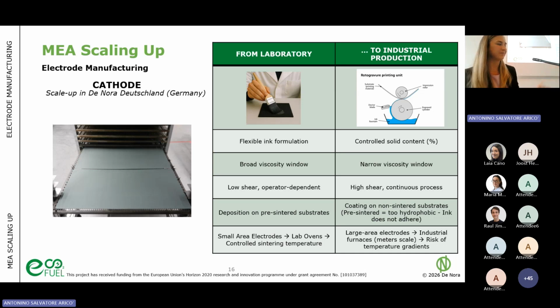Something is okay. And also in this case, what we need to consider, starting from the lab to the industrial scale. In the case of the lab, what we normally do is using a brush. So that's what we do in the lab. And in this case, we can work on flexible ink formulation, because it's operator dependent, the way we do the GDE. It's a low shear instead of the high shear in the case of the continuous process.